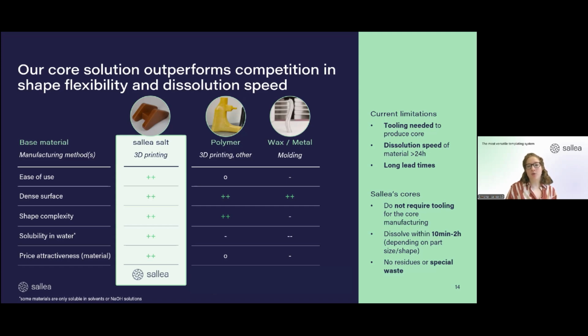Regarding shape complexity, of course, the polymers that are 3D printed have a similar advantage as we do. However, the ones that are molded are still quite limited in the shape. And last but not least, what is super important is the solubility or the removal of the core. For wax and metal, it has to be molten out. Often there is also something remaining inside. It's a bit of a nasty process. This, of course, is nicer for the polymer ones that are water soluble, but they take quite a long time. And of course, salt, you can imagine it when you cook pasta, salt dissolves quite fast. And looking at the price, also there, salt has quite an advantage compared to the other solutions.